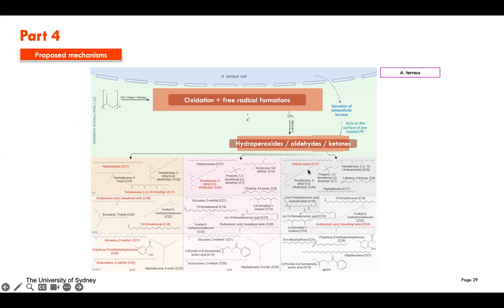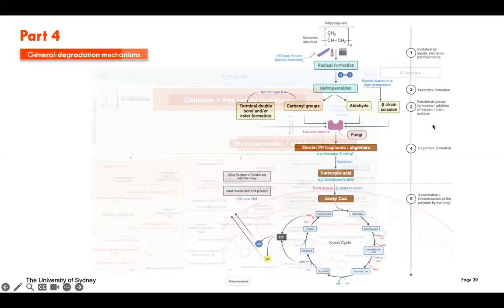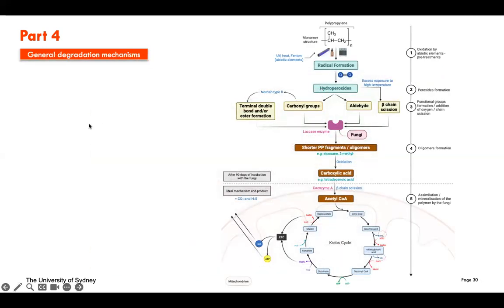So basically, the reaction, I can't show you the detailed reaction, but after the pre-treatment, there are oxidation and free radical formation. After that, they undergo a Norrish type 2 reaction and produce hydroperoxides, aldehydes, and ketones. That's what we got after we analyzed using GCMS, right? But I can show you this. This is a general degradation mechanism that I proposed, and I put it in my thesis. So hopefully the examiners understand this.